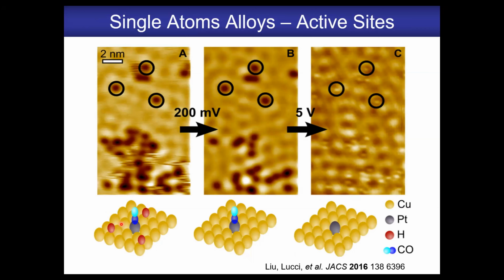So basically, I'm just showing you this model should be correct. Then we image at slightly higher bias, which basically sweeps the hydrogen away from the area. And now you just see dark spots there, which is every platinum atom as the surface is capped by CO. And then we pulse each CO molecule at 5 volts, tunnel into the LUMO, desorb the molecule, and then you can see the position of every dark spot here. Underneath it, there's a little bright spot, and that's the platinum atom in the copper surface. So this basically just tells you that the hydrogen spilled over onto the copper, and that we can selectively titrate the platinum sites with CO.